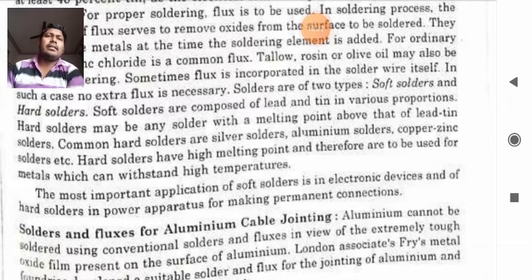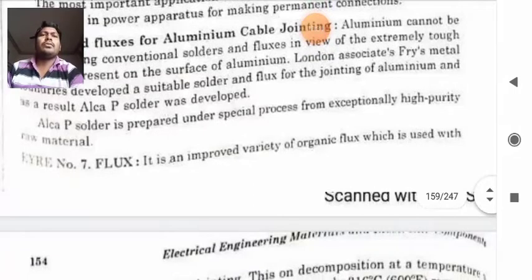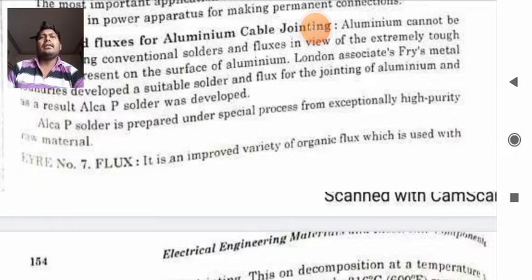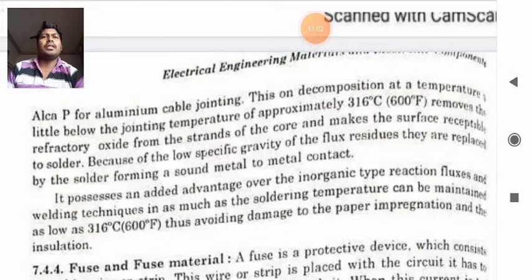London Associates Fry's Metal Foundries developed a suitable solder and flux for joining aluminum, and as a result Alca P solder was developed. This Alca P solder is prepared under a special process from exceptionally high purity raw materials. This is the flux. It is an improved variety of organic flux which is used with Alca P for aluminum cable joining. On decomposition at a temperature a little below the joining temperature of approximately 316 degrees centigrade, it removes the refractory oxides from the strands of the core and makes the surface susceptible to solders.